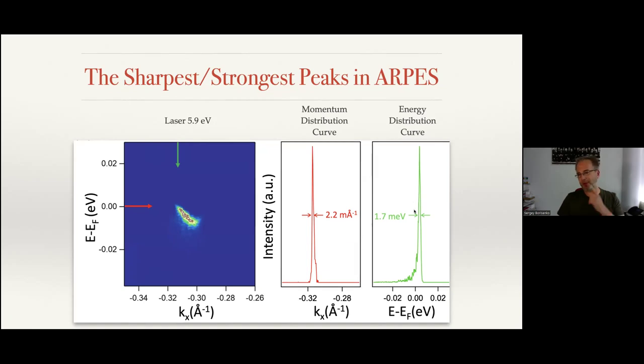Actually, both in terms of energy distribution, the width of this peak is 1.7 meV. This is not in terms of resolution, but in terms of the sharpness and strength of the peak, signal to noise ratio and its width. So this is 1.7, and also in momentum, this is 2.2 milli reciprocal angstroms. I always put 0.0 something, and our student, now postdoc, said, this is milli reciprocal angstrom. So now one could say a milli reciprocal angstrom is a 1,000th of a Brillouin zone. This is a very good precision.